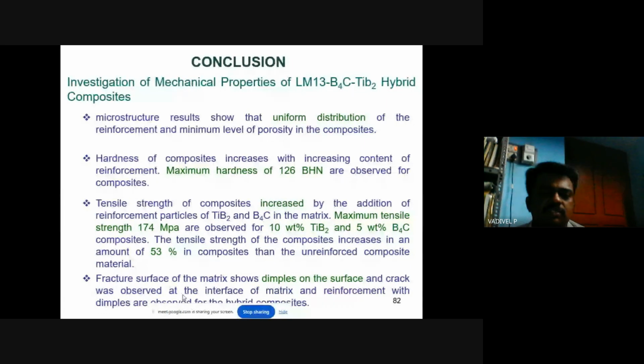In the conclusion, the microstructure result shows the uniform distribution of the reinforcement and a minimum level of porosity in the composites. For the mechanical properties, hardness increases with the increasing content of reinforcement, and the maximum hardness of 126 BHN is observed for the composites.